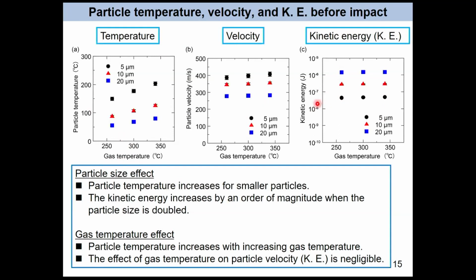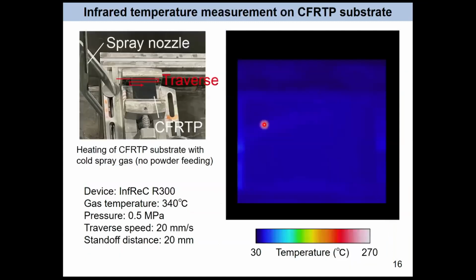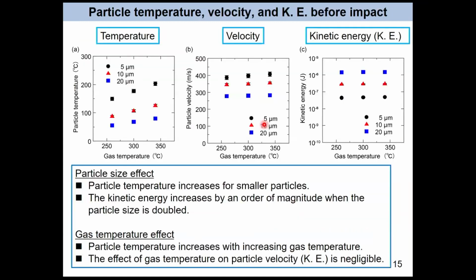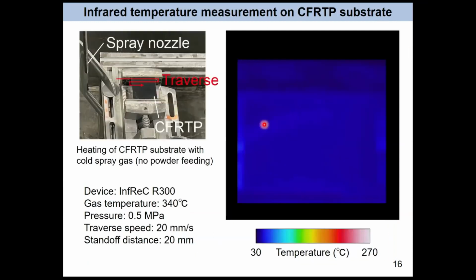For the gas temperature effect, the particle temperature increases with an increase in gas temperature. However, the gas temperature effect on kinetic energy and velocity was negligible in this simulation. So the gas temperature effects should be thermal effects on the particle and substrate. So we measured the substrate temperature by infrared photography.